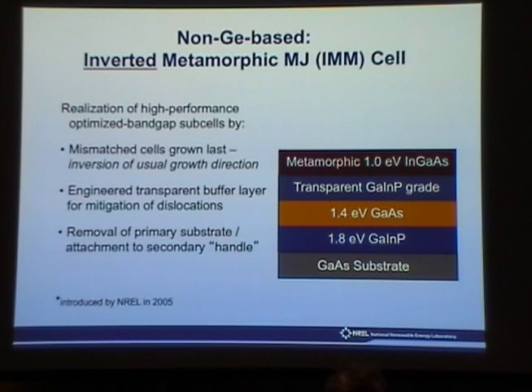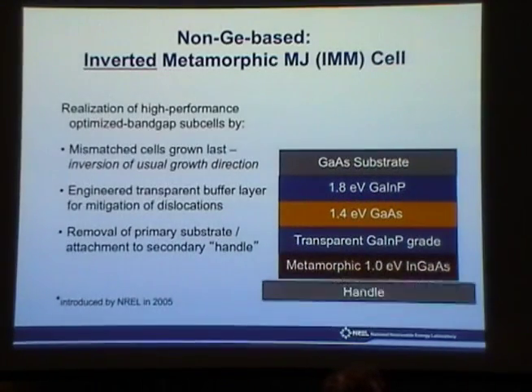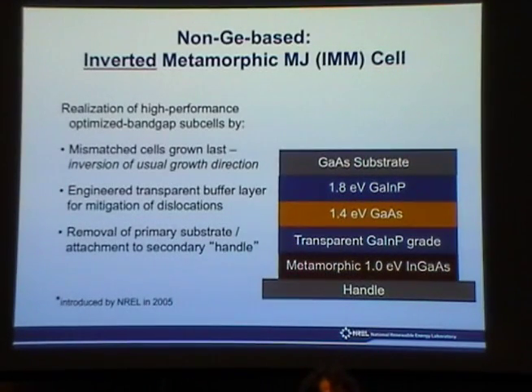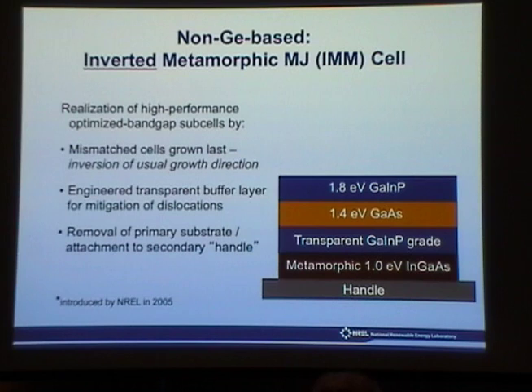So what we do is grow it upside down on the substrate, and then in processing, you flip it over and bond it to some handle, silicon, or whatever you want. You can bond it to glass, or to something flexible. Then we etch off the substrate, and then you shine light from the top. So this is the final schematic of this cell. It's very thin, maybe 10 microns. So 10 microns can easily be conformed to a flexible substrate. The space people love this because you've now eliminated the entire weight of the substrate. Just a note about space is that they have a different set of specs. What they're really interested in is efficiency per weight. And so they get rid of the weight of the substrate. They've reduced their launch costs.